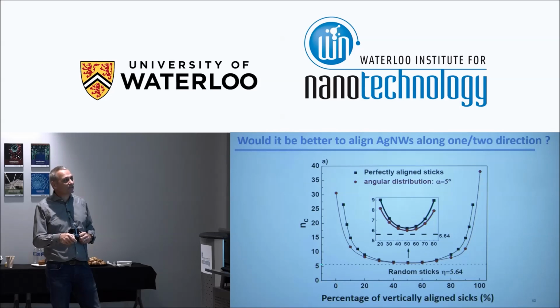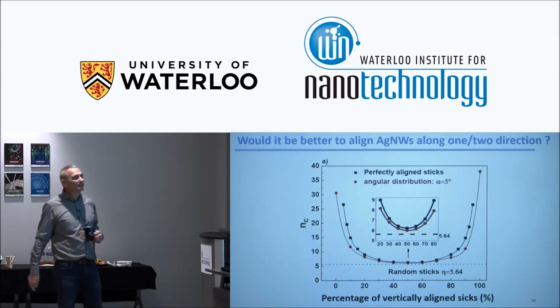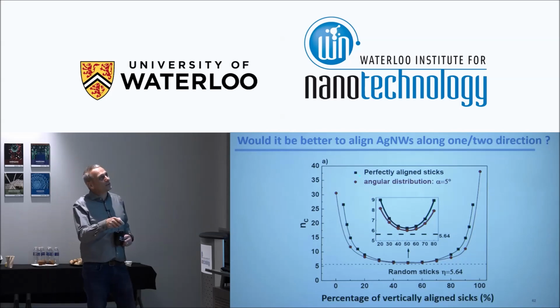What we show here is a random network, with 5.64 shown as a dashed line. If you consider trying to align the sticks, it's not very good. Here, in the zoom, we're still above this line. So for us, it's not that interesting to make them perfectly aligned, because in the Monte Carlo simulation, we